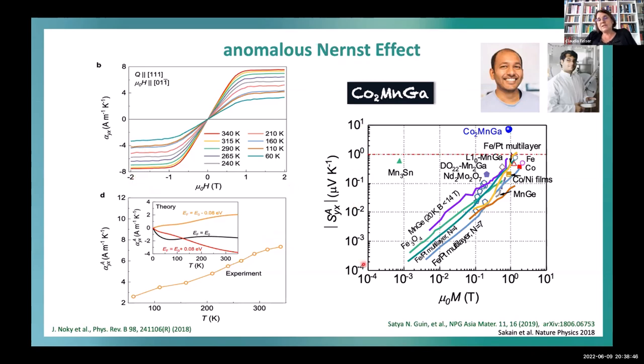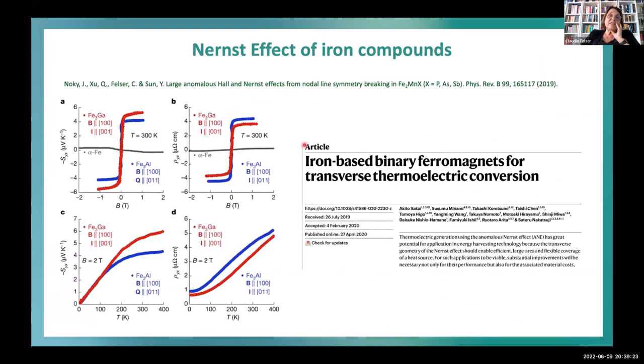And then if you see here the Nernst effect versus the magnetization, you see why people believed the Nernst effect goes with the magnetization, because this looks quite linear for most of the materials. You see that you have oxides there, you have intermetallics there. But now you see the values which are unusual, orders of magnitude higher, here is this cobalt 2 manganese gallium, and this is also a topological material. So for all the topological materials you see a giant deviation, and this is really an interesting area, even in direction of application. Even so, we predicted with the high throughput calculation, and predicted also, despite our experimental work, some interesting values, even higher values for iron 2 Heusler compounds.